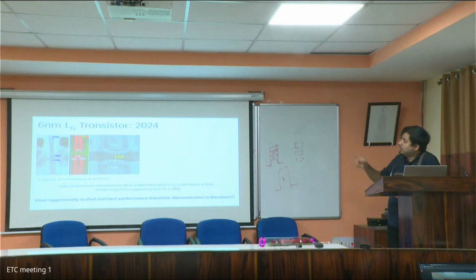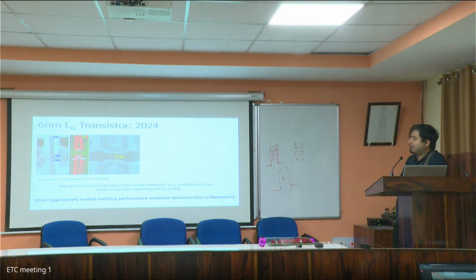Yep. So here you see 3.1 nanometer. In this paper, actually, the thinnest we have is 1.7. So the paper here was actually about how we scale the body thickness. If we scale the body thickness, that will also control the DIBL. So yeah, you modulate the electric field. Correct. So the way to control DIBL in nanosheet will have again the same knobs. Gate is the primary knob. The secondary knob is we can keep on thinning the body thickness till we get hit by the mobility of the thin channel. So that's how we take care of DIBL.